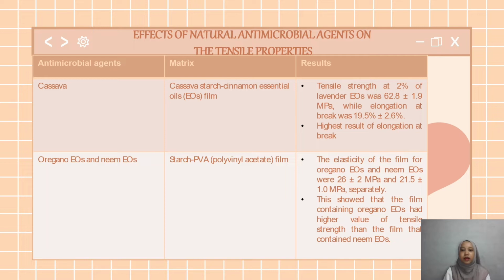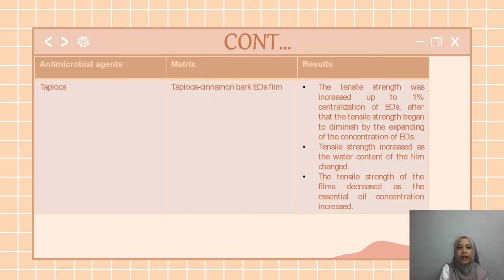The results are the elasticity of the film for oregano essential oils and neem essential oils were 26 plus minus 2 megapascal and 21.5 plus minus 1.0 megapascal separately. They show that the film containing oregano essential oils had higher strength than the film that contained neem essential oils. And tapioca as antibacterial agents.